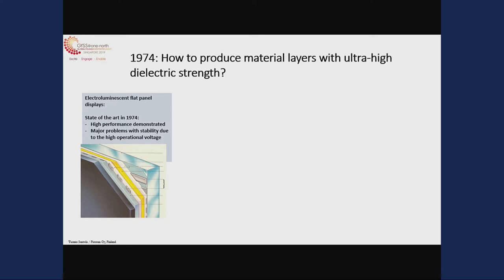Here we have the light emitting layer — the yellow one — and it is surrounded by dielectric layers, the white layers in the picture. I had some experience with amorphous semiconductors, and the key lesson was that if we need to have well-controlled electronic properties, we need materials with highly ordered material structure. Semiconductors traditionally are built on single crystal materials, but when we need to build up something else, the materials are not necessarily single crystals, but they should be as well ordered as possible.